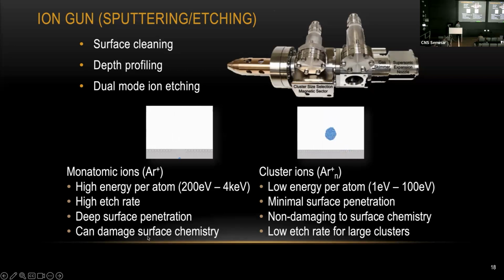your surface much more. So that's why most of the time, if you're working on any delicate sample, any biological sample, polymer sample, any sample where you want to preserve the chemistry on the surface, you can use the cluster ion source to do the cleaning. For instance, in the past, we tried some cluster ion cleaning on a piece of graphene. If you use a monatomic ion, you're going to damage your entire graphene, and you're not going to see any signal. But you can use a cluster ion to do some gentle cleaning on the surface and still do the good measurement.